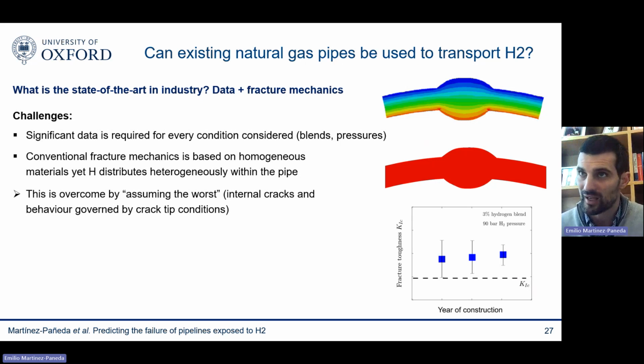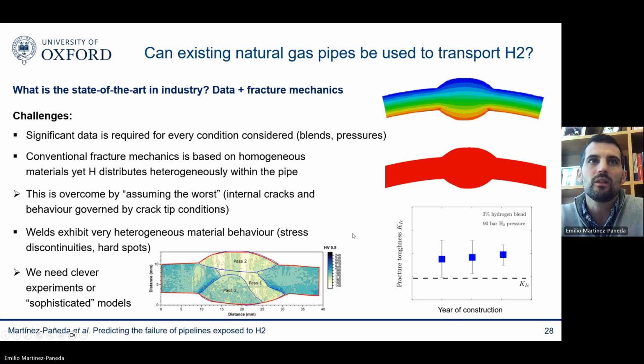I mean, I believe in fracture mechanics. It is true that it's, to a certain extent, conservative, although not too much, because it makes sense that inner cracks, in principle, one would imagine to be the most critical ones. And in principle, one would imagine that everything will be governed by crack tip conditions. So it makes sense that the condition that actually matters is not too far away from reality. The problem lies here, basically.